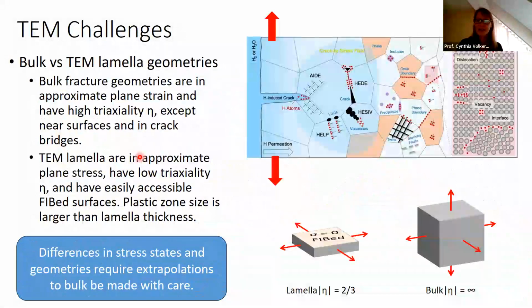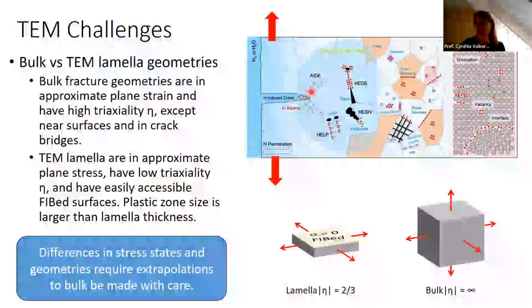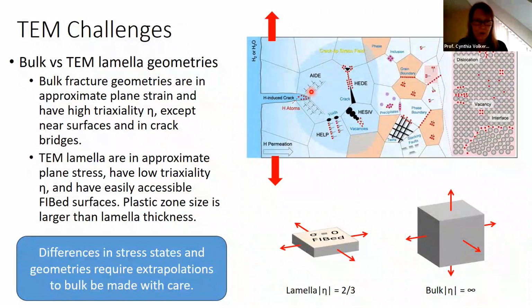And now the challenge that I brought up at the beginning, which is how do we actually control crack propagation in a specimen in the TEM? And here I'm using this sketch from the Max Planck again for a specimen that's being pulled on under tension. And it's easy to see that one would expect that this stress concentration that results at the head of this crack tip is going to lead to propagation of this crack.